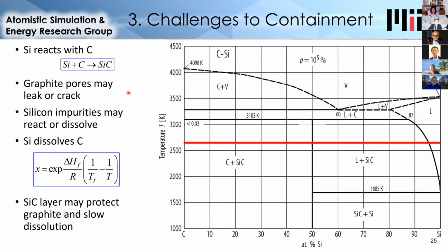So the challenges to containment that we predict is, first of all, silicon and carbon react to form silicon carbide. This has been known, and it's also known that under some conditions, this reaction forms a thin protective layer through which carbon and silicon diffuse so slowly that the reaction is slowed down drastically, even for a thin layer, a few microns thick. However, if the graphite has large pores, the silicon may leak out of the containment before the pores are filled by silicon carbide.